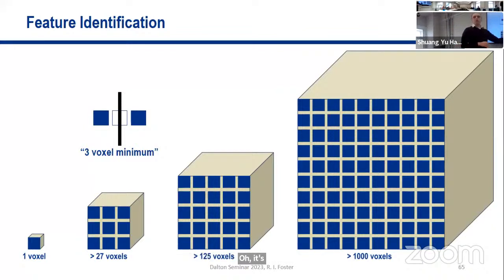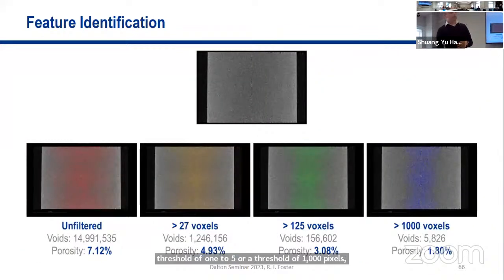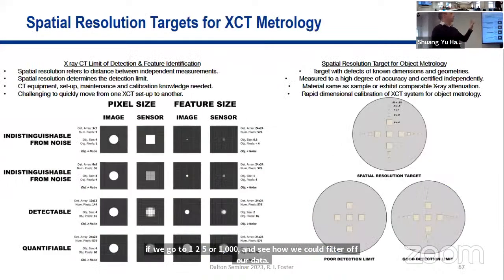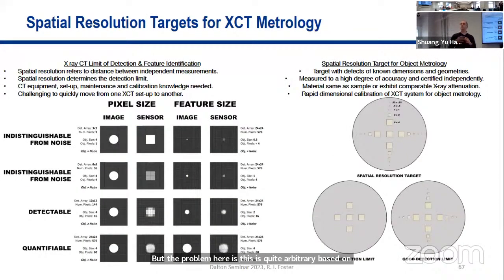But that's only a theoretical limit, or a theoretical threshold, essentially. What you need to do is actually have more confidence in that, and actually, are you confident to say what you're actually seeing? So you could then say, well, we have a threshold of 125 or a threshold of 1,000 pixels, let's say. So if we look at a set of data, this is one of the data sets that I've quickly analyzed. If I look at the voids unfiltered, we've got a measure of porosity of 7.1%. But the problem with this is counting all individual pixels. If I say, okay, I'm going to have a threshold of 27 pixels, then again, we've got a lower porosity because now we're eliminating some of those smaller individual pixels. Again, if we go to 125 or 1,000, you can see how we can filter off our data. But the problem here is it's quite arbitrary based on just individual pixels and an arbitrary number.